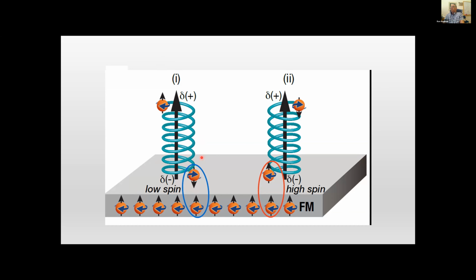The surface induces a dipole in the approaching molecule. Now, because the molecule is chiral, the induced dipole means charge is redistributed in the molecule. The charge is redistributed on the helical potential, and therefore there is a spin polarization. So actually, each electric pole is now associated with a spin polarization.